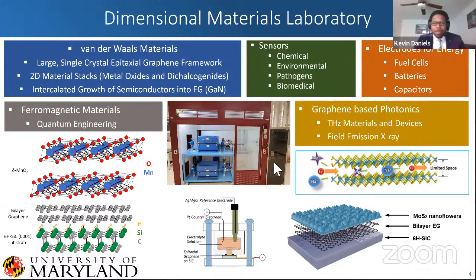And my lab is mainly focused on the synthesis of these materials and then fabrication of these devices. And so here we have, again, this chemical vapor deposition system for fabricating some of our materials. And then down here is what's called an electrochemical cell, where we can place our graphene here. We have electrolyte solution, and we're actually able to build materials by applying a potential in that manner. And this is how we actually synthesize this delta phase manganese dioxide for sensing.